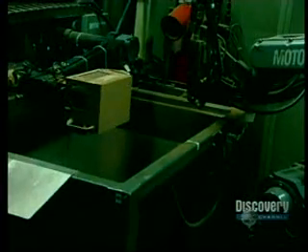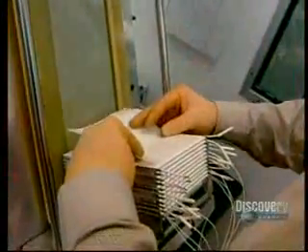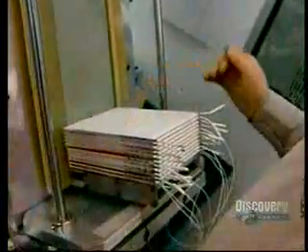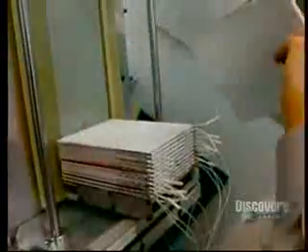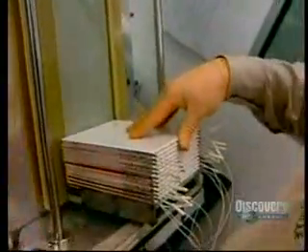It is comprised of 4 elements: lithium, which acts as the anode, a metallic oxide cathode, a dry solid polymer electrolyte, and a metallic current collector. All that remains to be done is the assembling of the individual battery cells into a module. It begins with the placing of individual cells onto one another and isolating them with foam so that they do not touch each other. These red sheets are actually heating elements, since the lithium metal polymer cells function at temperatures of between 104 and 176 degrees.